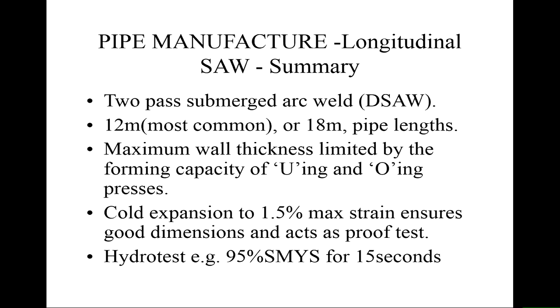So mostly for a UOE pipe, we have a 2-pass submerged arc weld, double submerged arc weld, DSAW, one inside, one outside. The wall thickness is really limited only by the forming capacity of the U-ing and O-ing processes. We could weld much thicker systems, but you need a very big press to actually press a 50mm pipe wall. You wouldn't do it. Most systems, 17-18mm is about the limit, and actually probably more like 10 to 12mm thickness is more the standard. Just depends on how much you're willing to invest in tons of press.